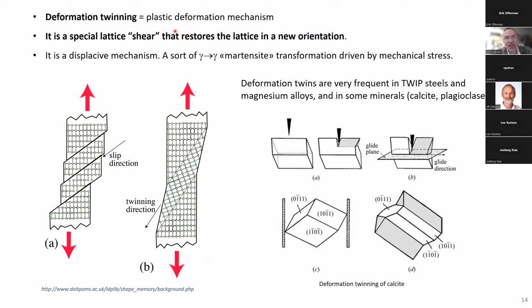Deformation twinning is a specific kind of plastic deformation. I think most of you know that we can plastically deform by dislocations, but there is also this mechanism of plastic deformation by twinning. It's a specific shear of the lattice that restores the lattice, but with a new orientation. We shear it, and for a certain value of the shear amplitude, we can restore this rectangular phase. To me, deformation twinning is really very similar to a martensitic transformation. It's just that the daughter phase is the same as the parent phase, and instead of being driven by chemical energy, it is driven by mechanical energy.